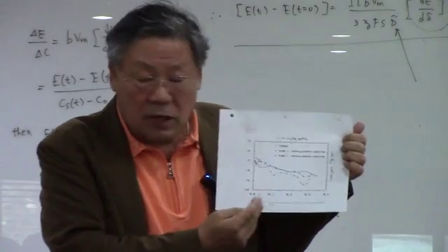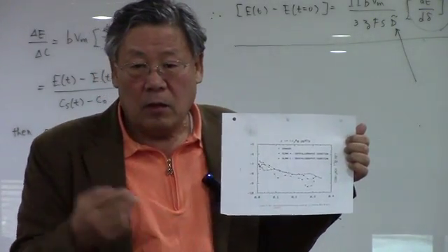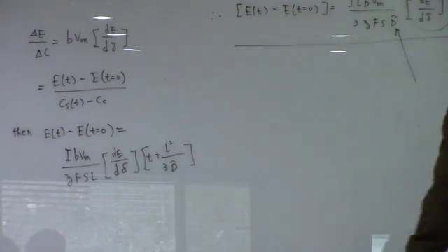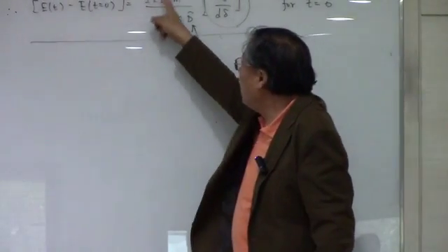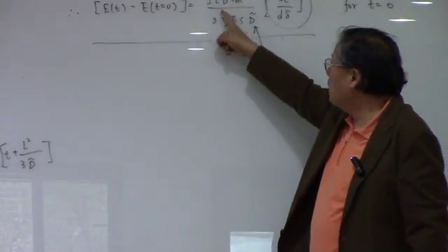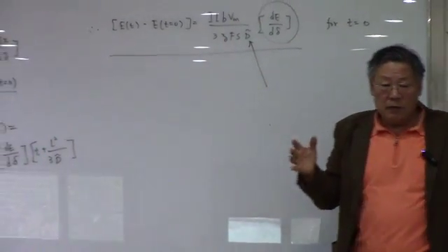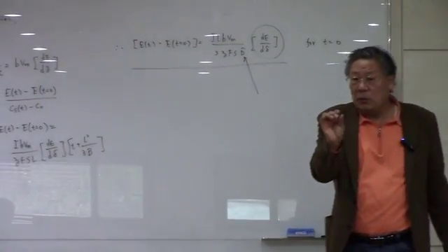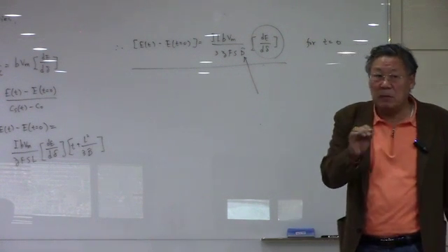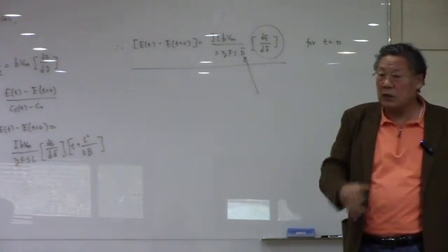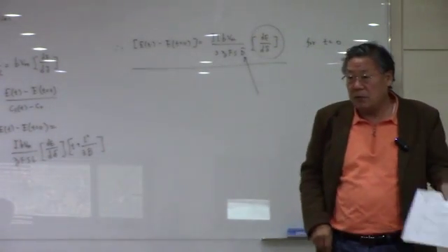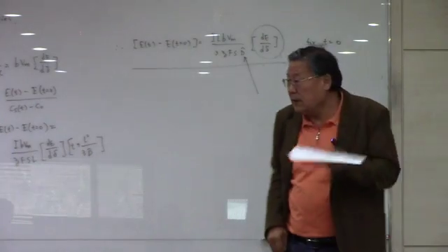But with the electrochemical technique, you set the coulometric titration curve to find the slope here. And then these values, molar volumes and B stoichiometric values, if you use a thin film, then that is a very small amount, so that it can be equilibrated very quickly, so that you can have data points very quickly and very precise, as you can see here.